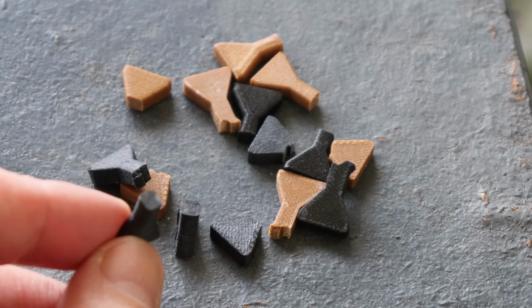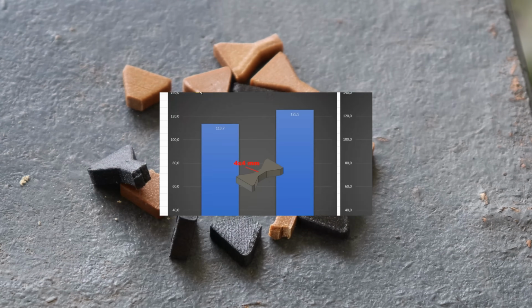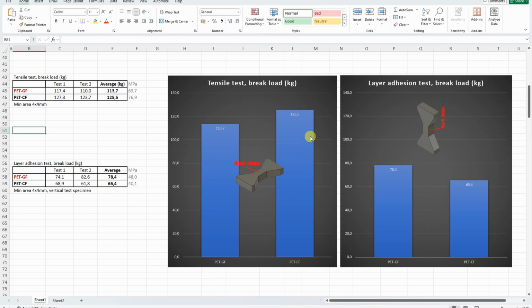Finally, a technical filament with great layer adhesion. On tensile test, small advantage on the carbon fiber version, but both are quite strong here. But this layer adhesion, even this 65 kg is good layer adhesion, but this is really incredible. And finally, we have a great technical filament reinforced with carbon fibers with a great layer adhesion.